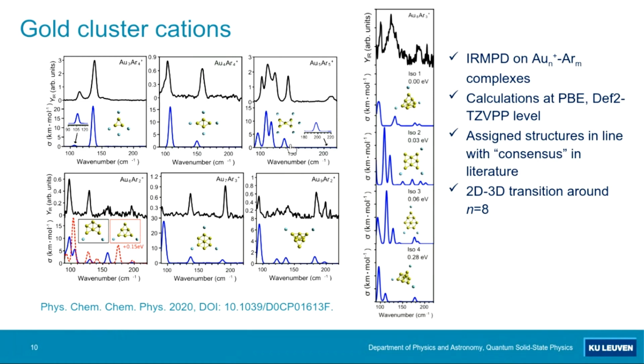It's not perfect. In this technique, you should not really trust the intensities of the modes, because the intensities depend on the dipole moment, and also on how steep the potential energy surface of these particles is, and that's something that is not always so well computed by DFT, but the energies should be quite sensitive. You see that the agreement is not perfect, but still you have all these modes and all other isomers miss completely the structure. You have others where the intensity goes down, but then still you can assign quite well gold 9, gold 7.